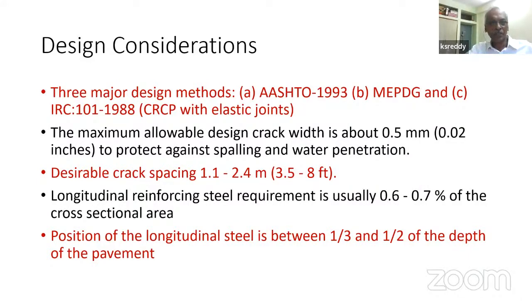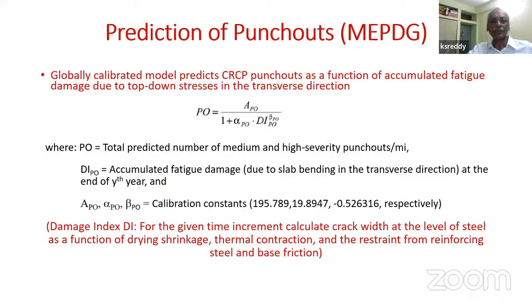There is a way of controlling that during the design process. Typically, the longitudinal reinforcement is of the order of 0.6 to 0.7%, and the longitudinal steel is placed at 1/3 to half the depth of the pavement.